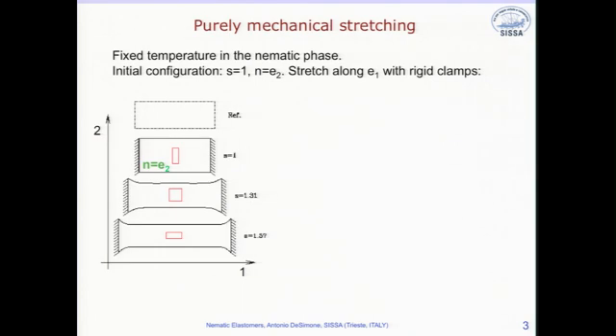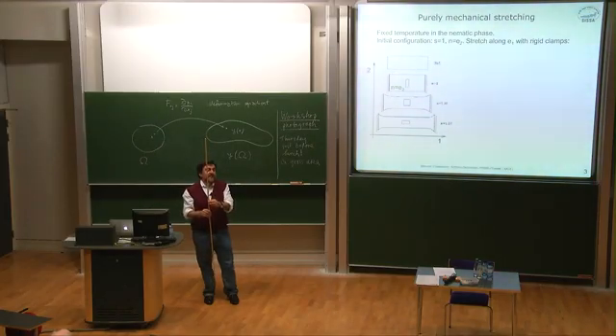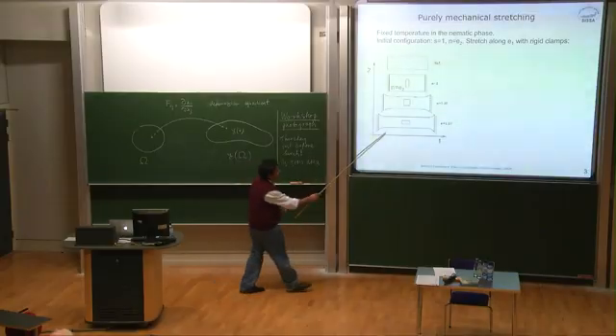So we have a material that is initially with the director uniformly aligned along the vertical direction in a thin sheet. And we stretch the sheet in the direction perpendicular to the initial director. This cartoon here is meant to remind you that if the director is vertical, the material likes to be elongated along the direction of the director. Now we pull in the opposite direction. I won't insult your intelligence. What the material decides to do is to have the nematic rods rotate to adjust to the external imposed stretch. And this is this cartoon here.